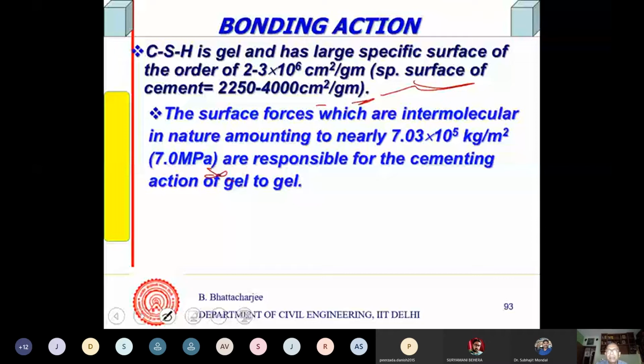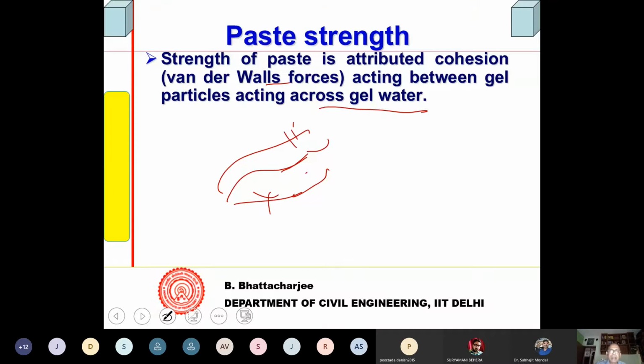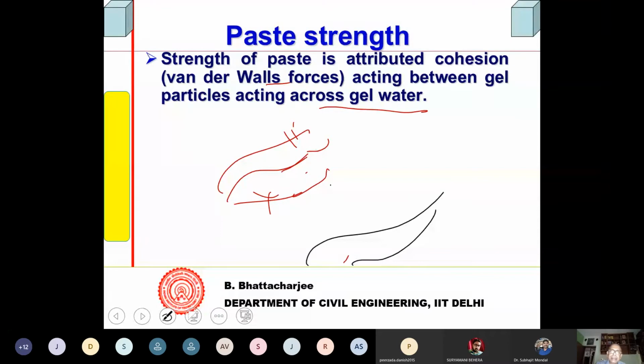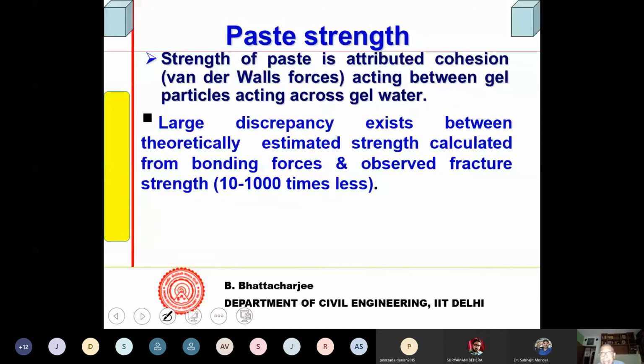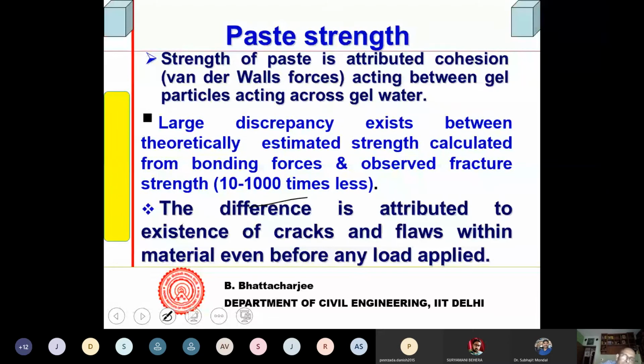The strength of the paste comes from van der Waals forces between gel particles. Between gel, of course, there are van der Waals forces because they are layered structures, as we have seen. But layer to layer, within the C-S-H, the bond is covalent, and between C-S-H it is van der Waals forces, and in capillary pores, of course, there is no bond. So the strength as calculated based on the bond strength comes out much higher. Therefore, this strength reduction is attributed to the existence of pores even before you have applied the load.